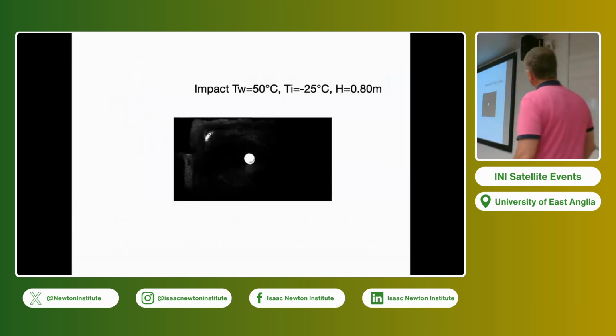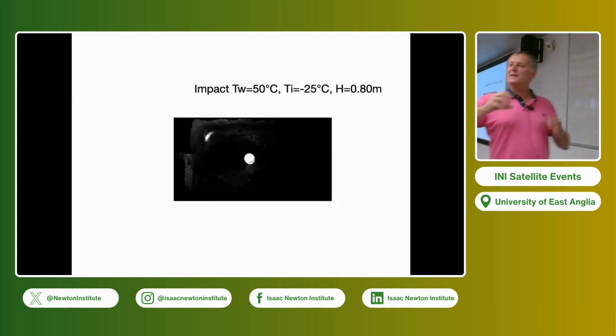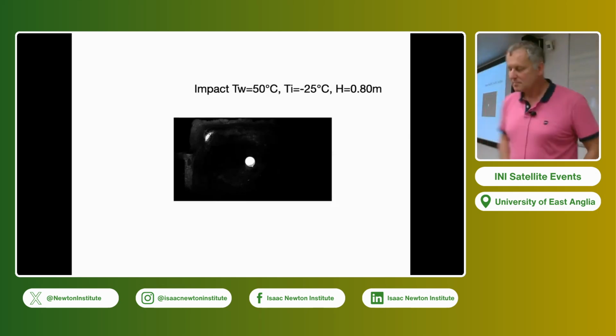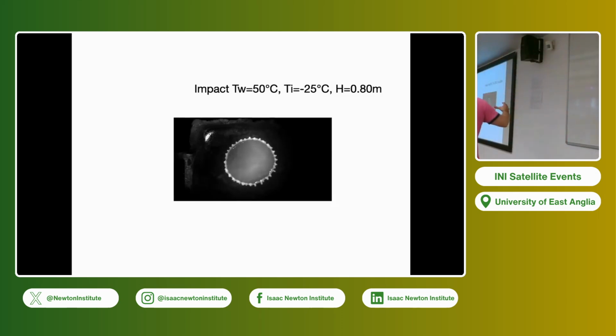And I will show you the impact of a water drop on an ice layer. We put some fluorescein on the drop in this case. That means you can see the fluorescein when it's liquid, and you cannot see it when it's solid. So the drop is spreading, and you see that you have some still water, and you have a maximum spreading radius.